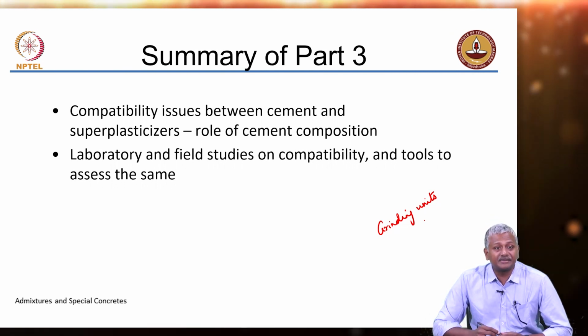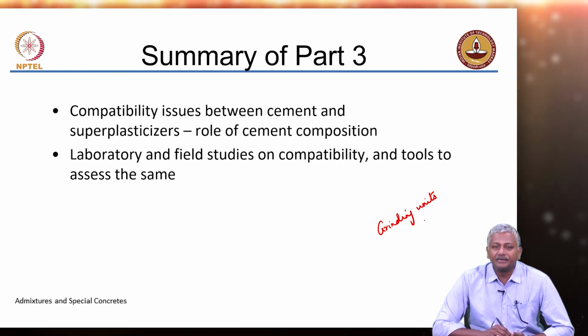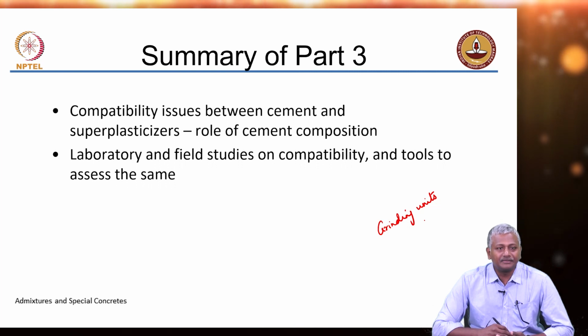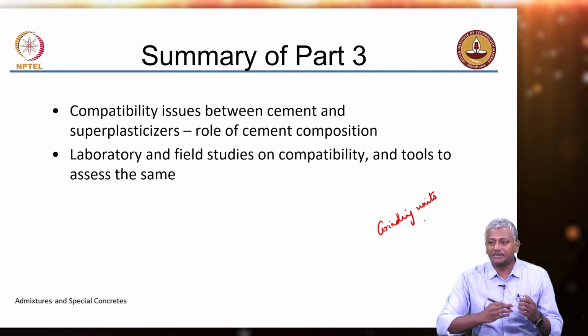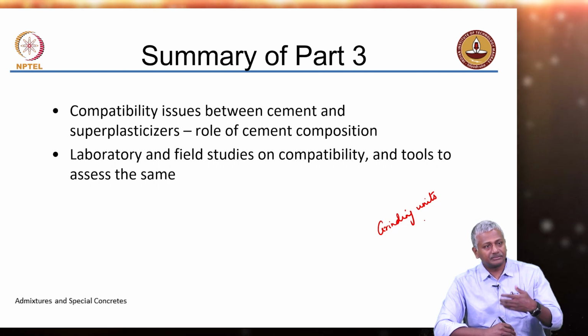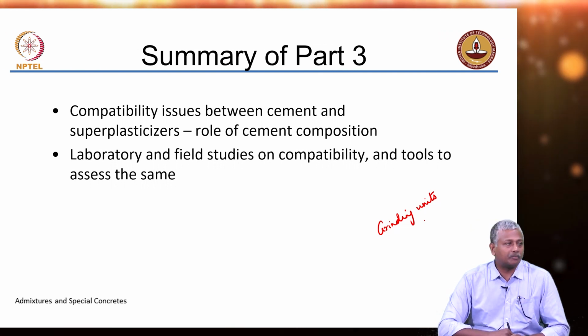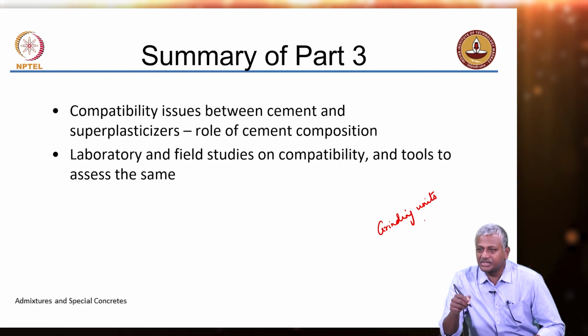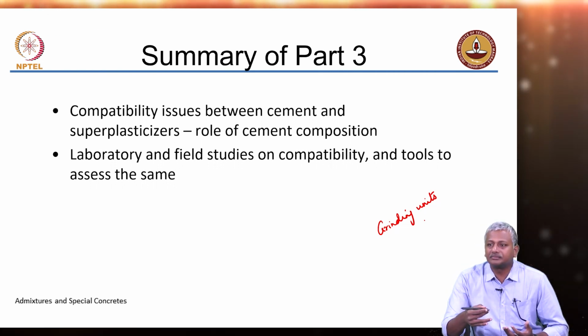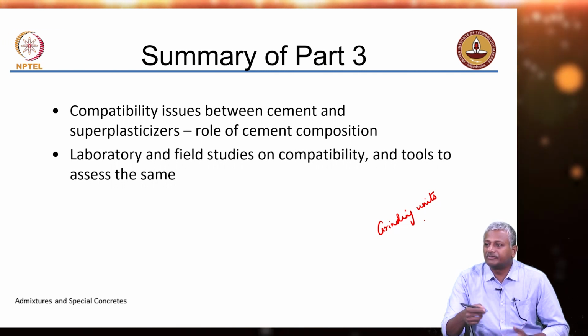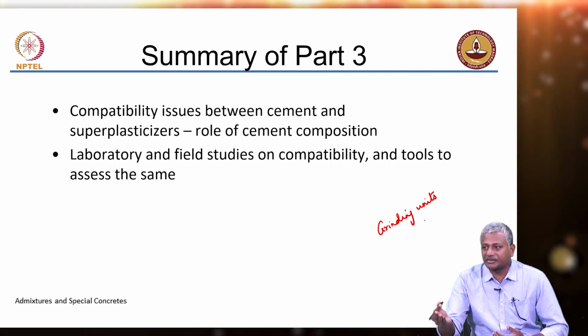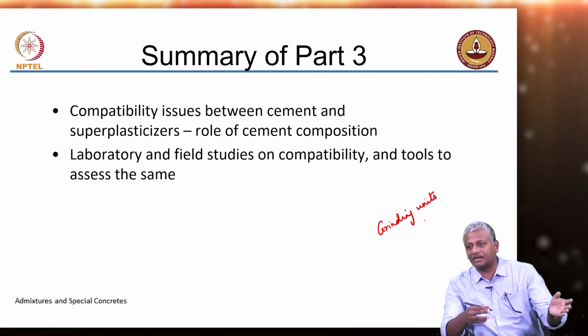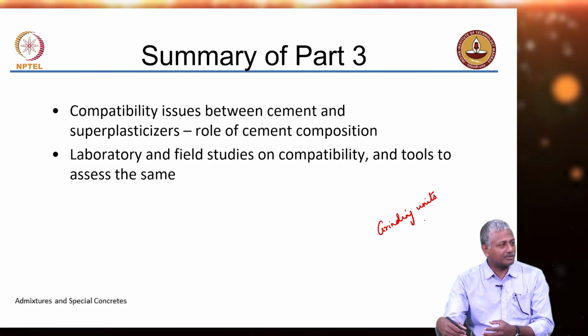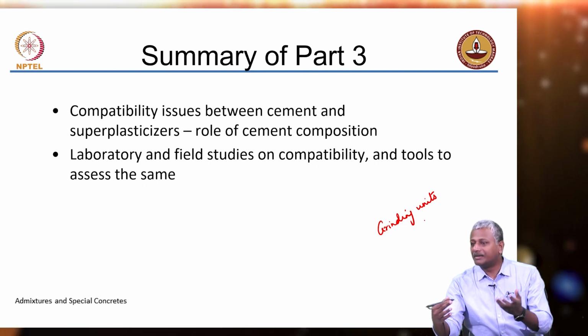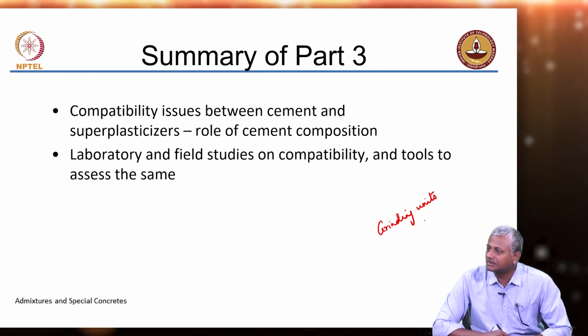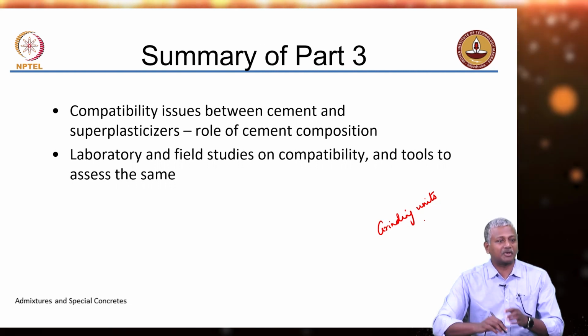And in one such case, this indeed was a problem. We saw that the primary source of the problem was the change in the cement clinker for the cement that was supplied to a particular project. But what happens on a construction site is that if something is not meeting the requirement, the first person to get blamed is the admixture manufacturer. Why is that? Because that is something foreign, that does not need to be there in the concrete. Cement is obviously important for the concrete, but why are they putting this admixture? It is something different, right. Some problem has happened, so it may be because of the admixture.